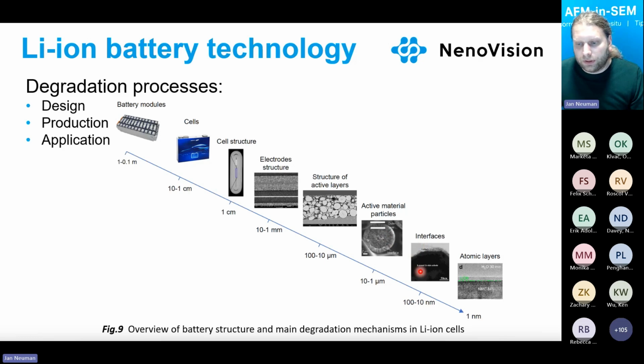Then we are also focused on studies of interfaces like the solid electrolyte interface on the anodes, and on high and really deep research on the studies of atomic layers, for example, lithium hydroxide on the surface of high nickel content NMC.